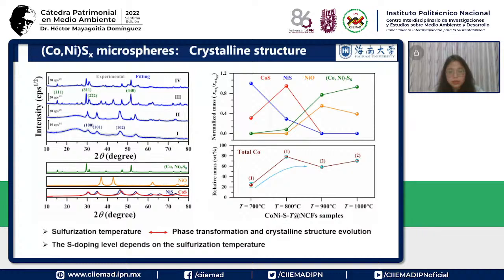And then we made a careful XRD analysis, and this work also comes from my friend Luis. He did this nice work and helped me analyze the XRD. We can see the 4 temperatures here, we heat treated at 700, 800, 900, and 1000. They show different components. When the temperature is 700 and 800, the major components are cobalt sulfide and nickel sulfide.